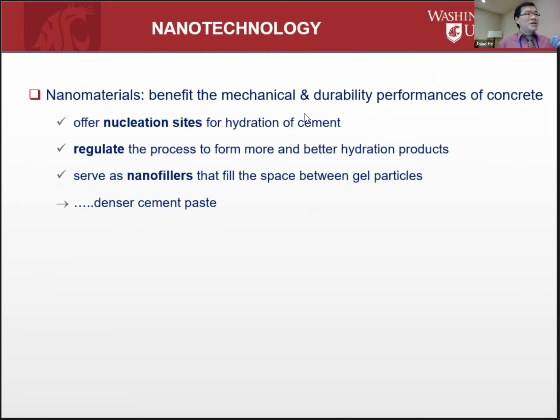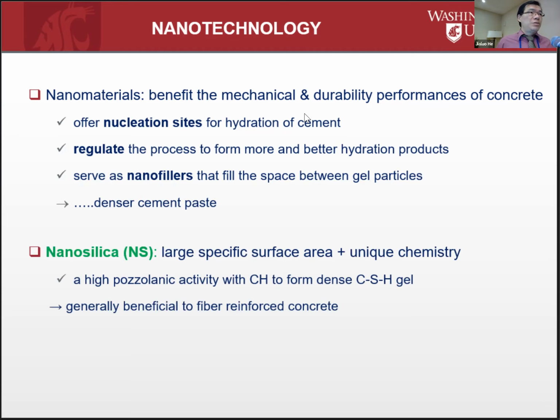So again, nanotechnology, we talked about this yesterday. Nanomaterials are not simply nanofillers, they actually work almost as catalysts, because they offer nucleation sites for the cement clinker to hydrate, and they also regulate the hydration process, so you end up with better, denser CSH gel. All of these effects contribute to a denser microstructure, better mechanical performance and better durability. Among all the nanomaterials, one relatively affordable material is nanosilica. In addition to all the previous mechanisms, it also features really high surface area as well as pozzolanic reactivity. In other words, it can react with portlandite in the cement hydrates to form additional CSH gel, making the concrete even denser and stronger.